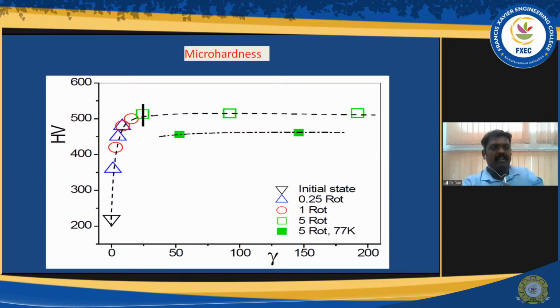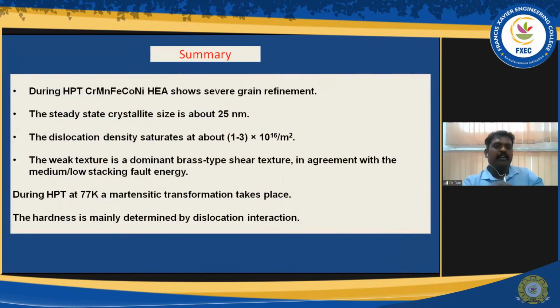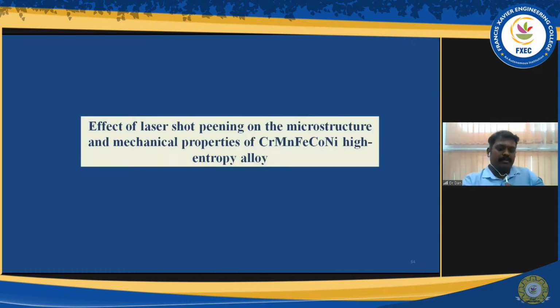That's what I wanted to say here. Also, we tried to measure the hardness of the sample. The hardness of the sample after 5 rotations is significantly increased, right? You can see here. So now, what summary can I give from this HPT process? They were able to refine the grains down to 25 nanometers. They got a very high dislocation density. Also, they understood that it has a weak brass-type texture after heavy severe plastic deformation. So that's what I wanted to emphasize.